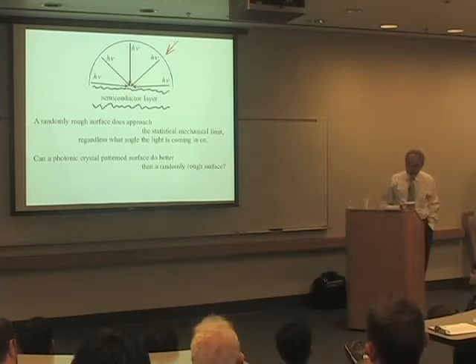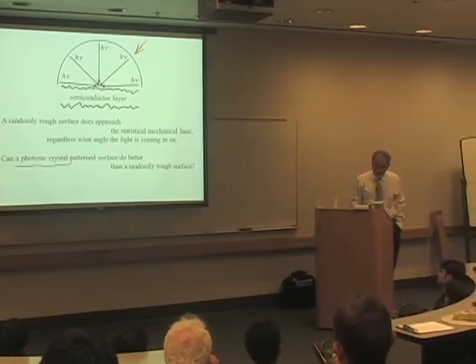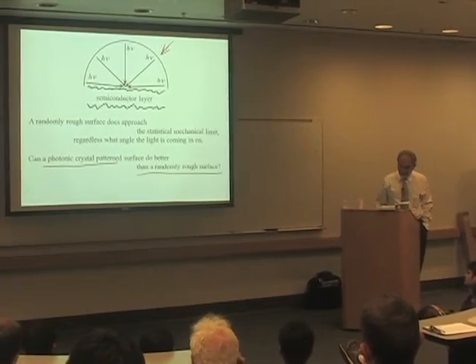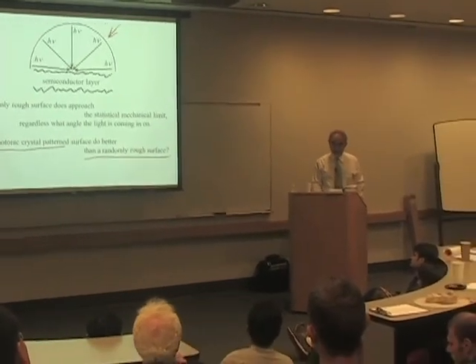However, I do get another question very often. Can a photonic crystal do better than a randomly rough surface? Well, in geometrical optics, no, because there's a simple theorem that says the randomly rough surface is the best. But we're headed toward extraordinarily thin solar cells that are thinner than half a wavelength. You're in the wave optics limit. The geometrical optics argument does not apply. And almost inevitably, someone will discover a particular photonic crystal pattern that is ideal for trapping sunlight in the wave optics limit in very, very thin cells.